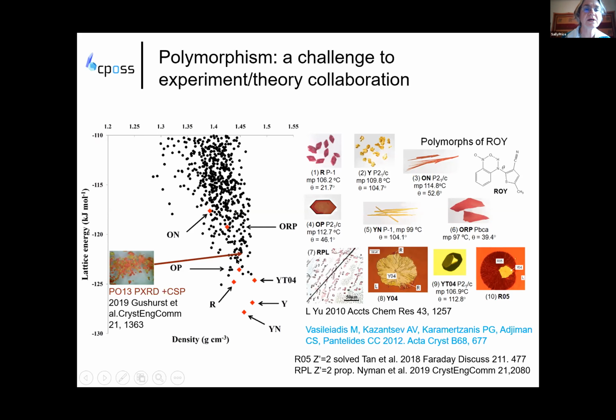Not quite sure why that's happened, but you've got a range, and later people were able to characterize two of these new polymorphs, which had two molecules in the asymmetric unit, and found another polymorph which had just one molecule and had been previously predicted. But you can see here that there are an awful lot of structures which have not been found. Yes, there are lots of polymorphs that have been found, but there are many more that haven't. And this is one of the embarrassments of crystal structure prediction.